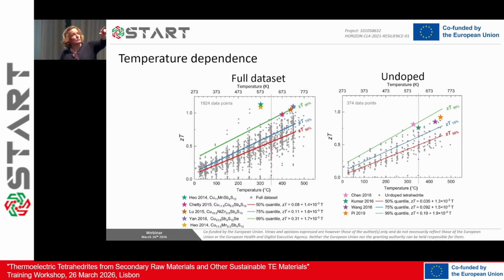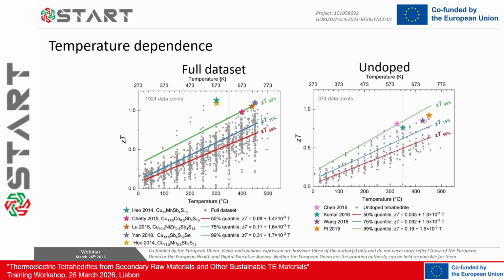But the conclusion we took from here is that there's a lot of weight from these points here that probably result from very poor processing, which are really pulling the average down. So maybe instead of using the average, these are percentiles - sorry, quantiles, that's the proper way to say it. These are quantiles.